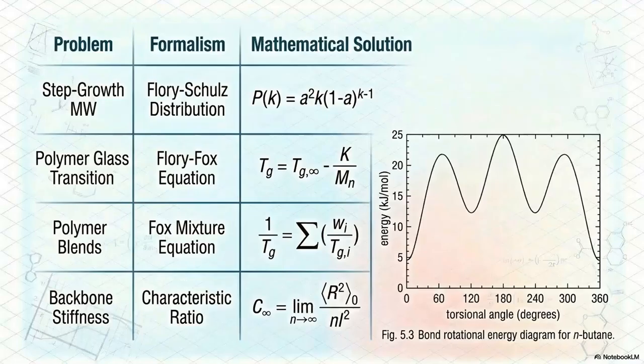This matrix presents Paul Flory's elegant mathematical solutions to 4 foundational problems in polymer behavior. First, for step growth molecular weight, the Flory-Schultz distribution provides a precise probability model. Second, the polymer glass transition temperature is defined relative to molecular weight using the Flory-Fox equation. Third, for polymer blends, the Fox mixture equation calculates the resulting transition properties of mixed materials. Finally, backbone stiffness is quantified using the characteristic ratio, C infinity.